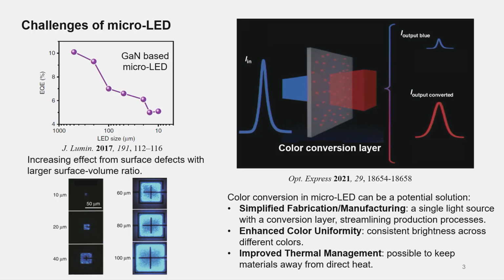We do believe there are several advantages to this approach. First, you could possibly simplify the fabrication process, because essentially you only need one blue light source, and then you can fabricate the color conversion layer materials individually. Because of that, you also have the possibility to enhance color uniformity, because the fabrication of the color conversion layer is separated from the blue LED at the bottom. Finally, you can also have some handle on the thermal effect. You can place the color conversion layer away from the LED, so you can mitigate some thermal effect.